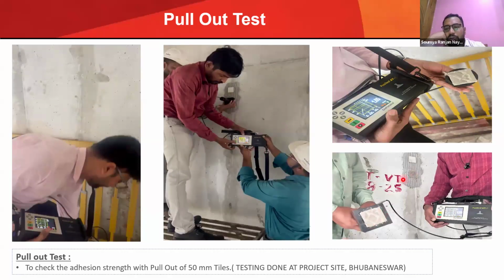You see how the tile debonds from the substrate and the tile adhesive breaks at 1.30. Okay, this kind of test we do to ensure the strength of tile adhesive.